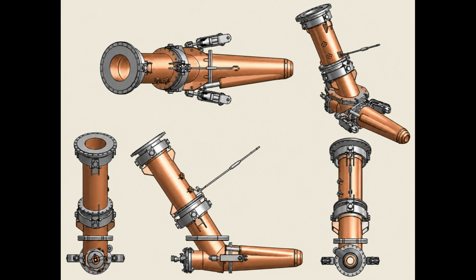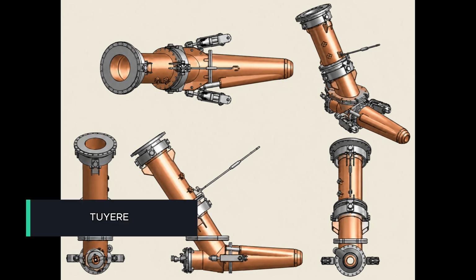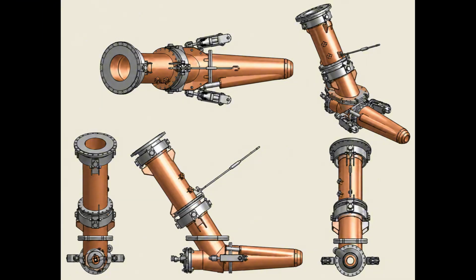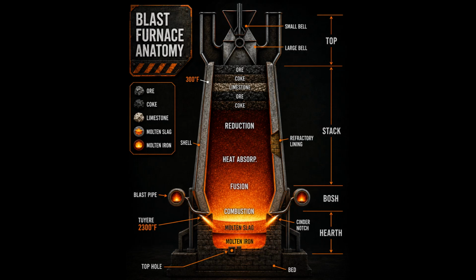At the base, a ring of copper nozzles called tuyeres injects preheated air directly into the coke bed. They are made of copper and they survive internal temperatures exceeding 2,000 degrees only because they are continuously flooded with cooling water. Stop the water for even a short time, the tuyere melts.